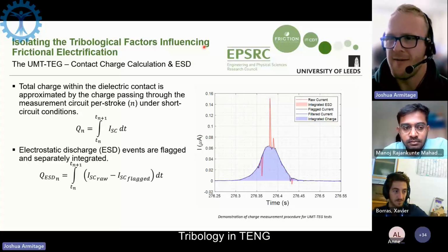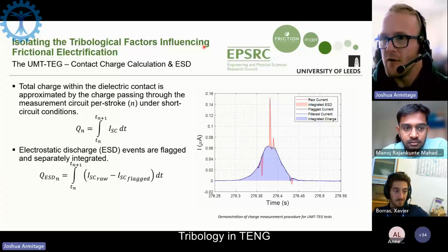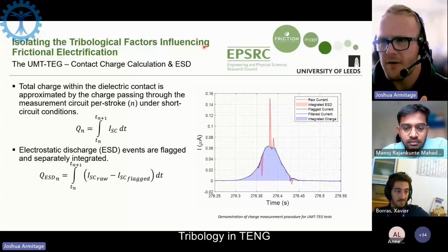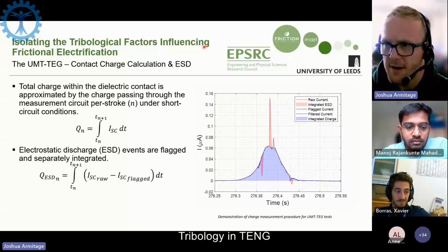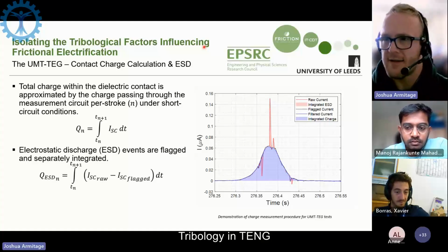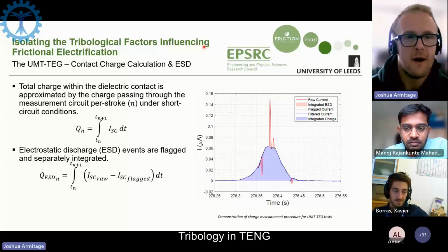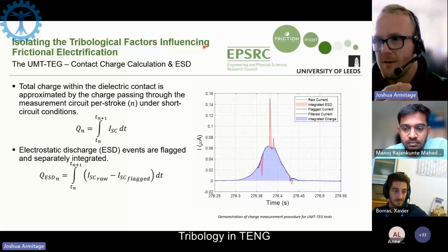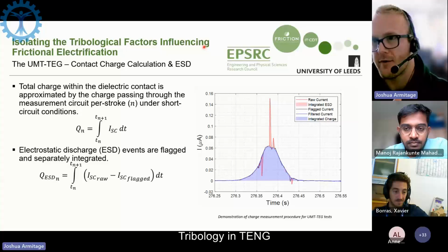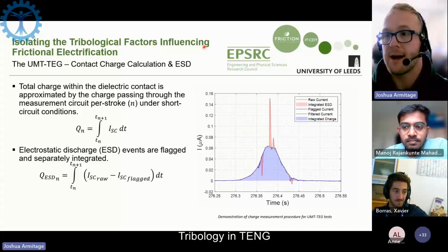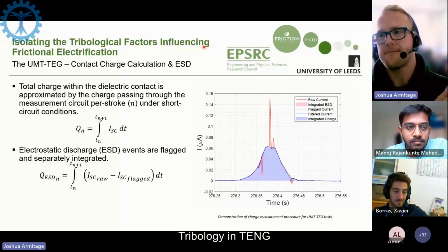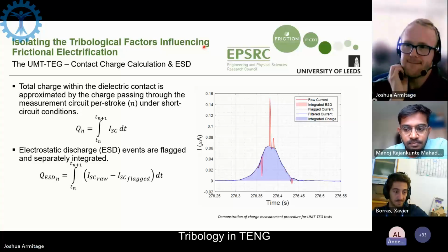We're also trying to determine the nature of these events. My current understanding, and what I believe them to be at the moment, is this: we've measured the charge value for each one, and it's roughly a few thousand electrons being moved at a given time. So it's striking me as, rather than the movement of an ion, like a very small bit of wear debris moving across the contact, more like an actual electronic phenomenon. Okay, thank you very much.